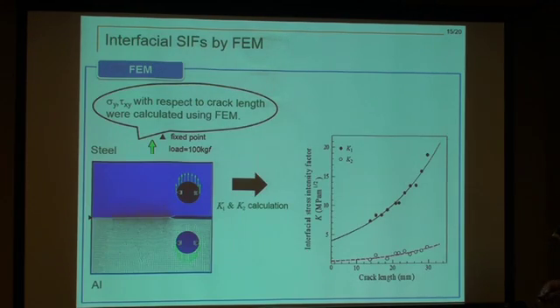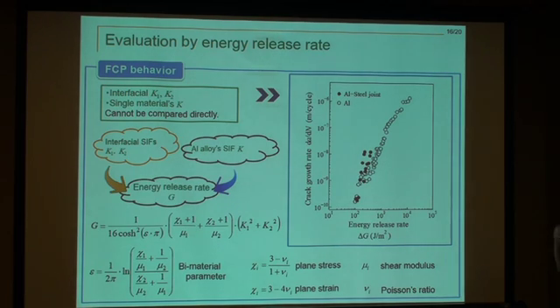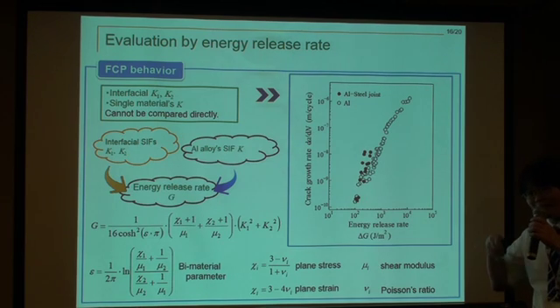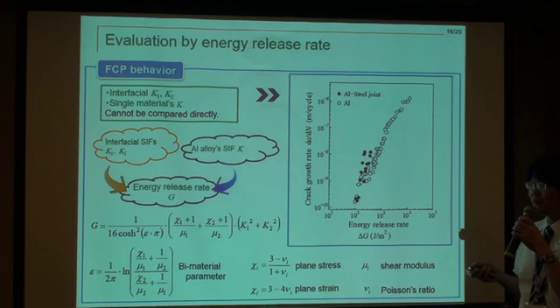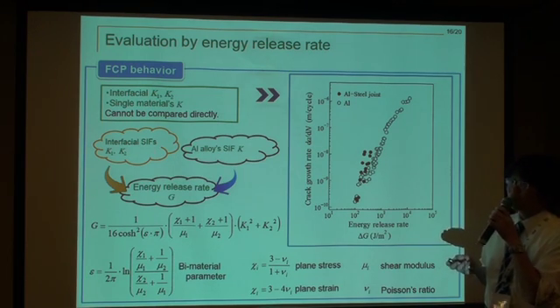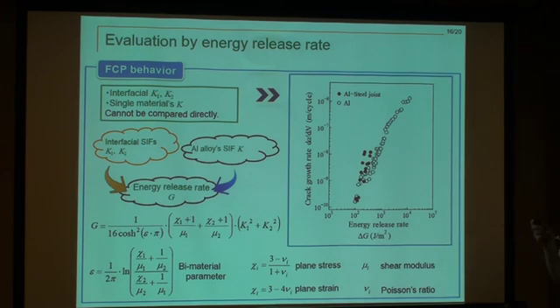There are several ways to calculate the stress singularities in the interfacial crack. Here we first calculated the stress field near the crack tip using a commercial FEM code called Nastran, and after we calculated the stress field by the extrapolation method, we calculated the stress intensity factors in mode 1 and mode 2 respectively with respect to the crack length. And even after the calculation, those interfacial mode 1 and mode 2 stress intensity factors cannot be directly compared with the single material's stress intensity. So we calculated the energy release rate by using the interfacial stress intensity factors. And now we can evaluate the crack growth rate with respect to the energy release rate.